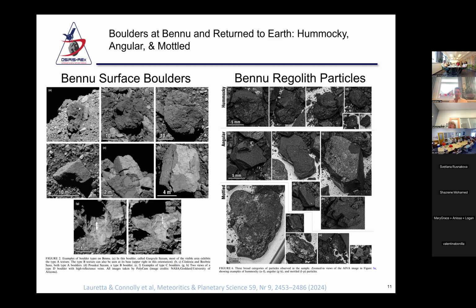There were almost 200 impact craters on the grains. I think there were only 4 grains in this particular paper that were the contact pad grains. So there was a significantly greater distribution of micrometeorite impact cratering on those. The general regolith, it was much lower. Only about 20% of the grains, between 10 and 20% of the grains, showed these micrometeorite impacts, or at least that we could find.